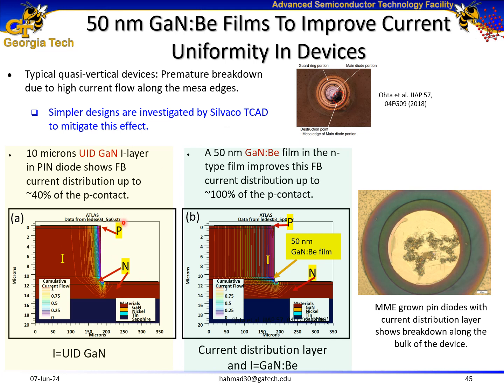In this regard, I did a comparative study of 2 pin diodes, both with I-layer thicknesses of 10 microns. The difference between these two is that the right structure has a thin 50 nanometers of beryllium-doped gallium nitride film sandwiched inside the n-type layer, which would introduce a small barrier, resulting in more uniform current distribution across the device. As we can see, the current distribution improves from approximately 40% to 100% of the p-type contact of the device. And later I have shown in one of my devices that now the breakdown occurs across the bulk of the device and not along the mesa edge.